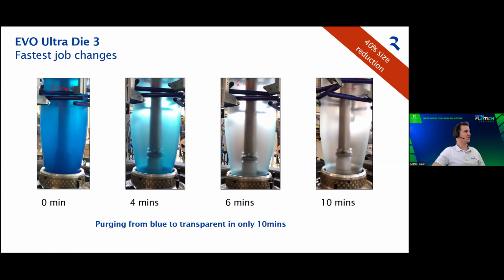Here we're showing on this 3-layer die head a job change, purging from blue to transparent, for example, in less than 10 minutes, which is a very nice value that you can achieve. And this is done by having this smaller and compact die head.